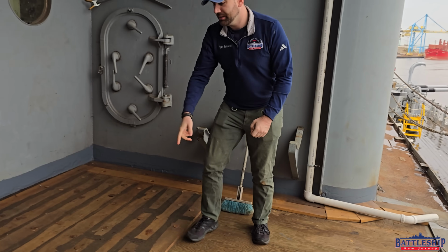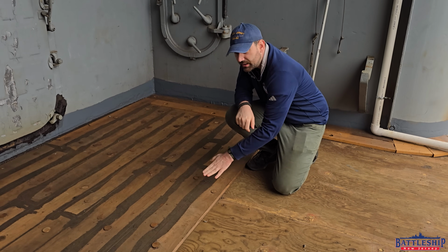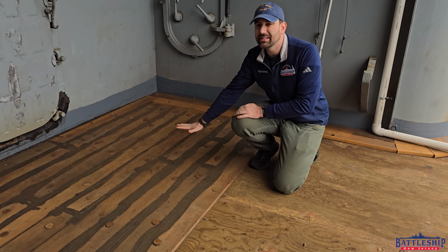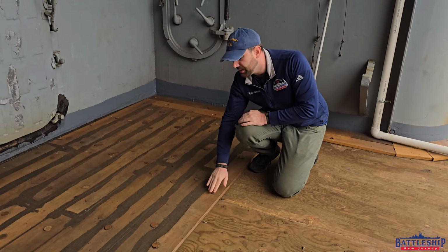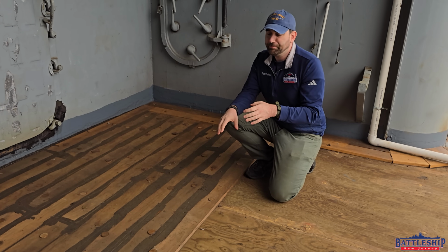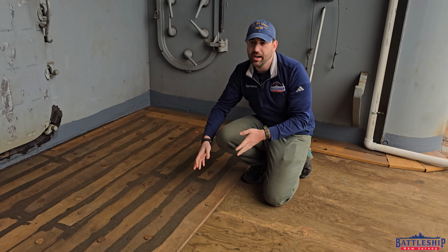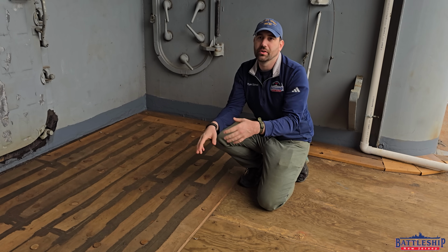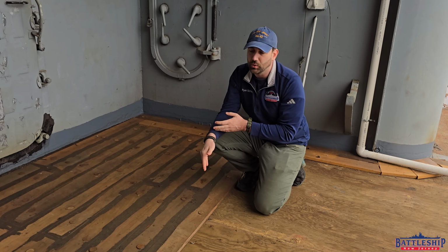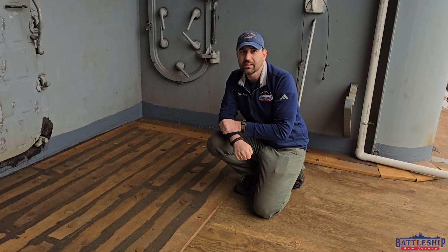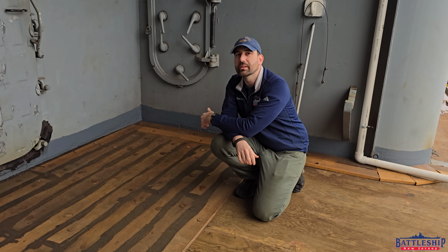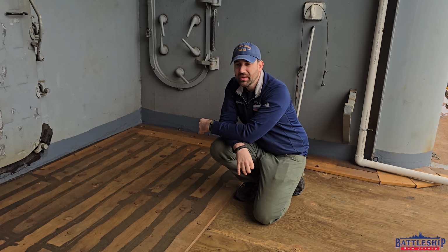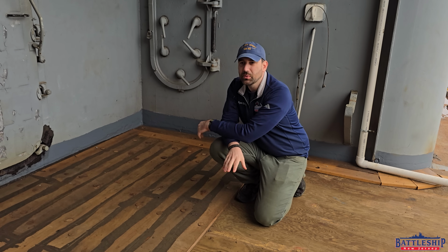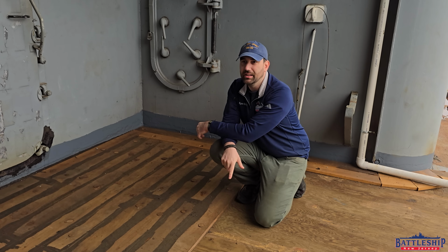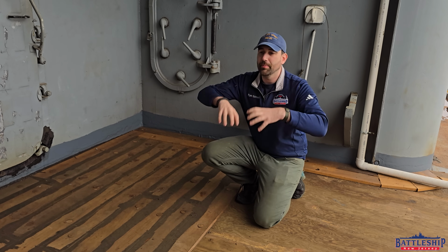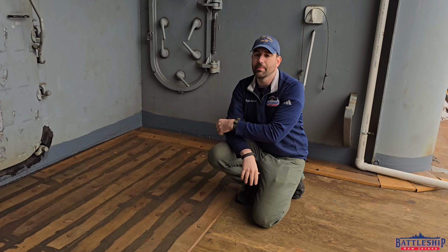Coming over here to some of the teak, you can see the studs get capped with plugs. This part of the deck has not been sanded yet, so that'll get rid of all this overspray and where this is not flush. But water is able to get in here over time. It's obviously protected with adhesive and hydrophobic stuff, but over time that breaks down, water gets in, and now each of these holes that's cut into the plank will allow water to get through to the steel underneath. And that's really where the issue is. We're less worried about the wood rotting, more worried about the steel underneath getting wet and starting to bloom up and then breaking these studs and the wood coming apart.